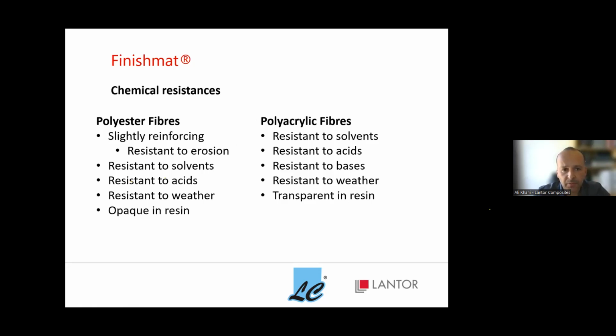So basically in terms of chemical resistance, the veils which are made of polyester fiber are slightly reinforcing. They help to resist against erosion, solvents, acids, also weather and harsh conditions, but they are opaque in resin. So if this is, for example, a carbon visible laminate, we usually advise to use the PAN-based or polyacrylic fiber-based veils, because that one becomes transparent in resin. And these PAN-based fibers are also resistant to solvent, acids, bases, and weather.